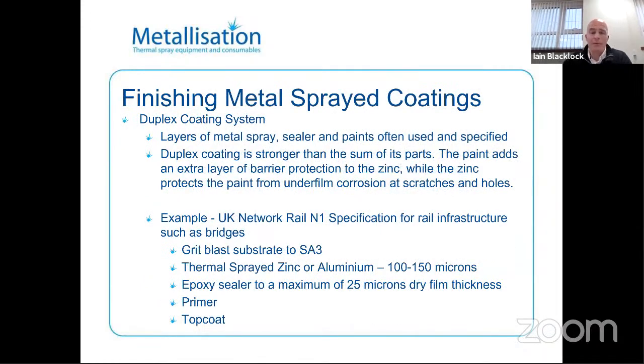So finished metal spray coatings, duplex coating systems. This is generally layers of metal spray, sealer and paints which are specified for given applications. The duplex coating is stronger than the sum of its parts, so the paint will add an extra layer of barrier protection to the zinc, while the zinc protects the paint from underfilm corrosion and scratches and holes.